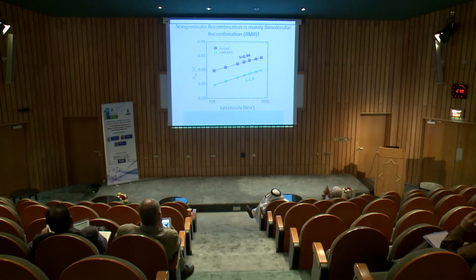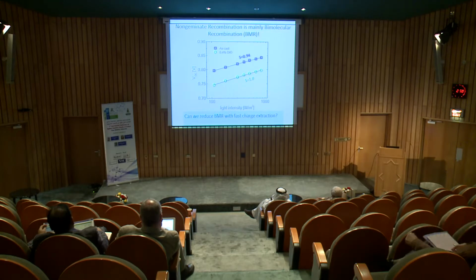So here I plot open circuit voltage as a function of light intensity, and you can see the slope of both devices is close to 1. So it means that the only type of non-geminate recombination loss in the two devices is bimolecular recombination. Now the question here is, can we reduce bimolecular recombination with fast charge extraction? The answer is yes, if you have very high charge carrier mobility.